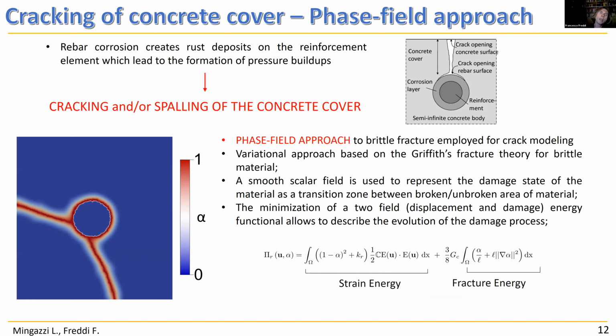So once the expansion and the swelling is determined, the fracture process has been studied with a smeared approach. I don't know if you are familiar, just a few words. The sharp approach to fracture is extremely complex because the most difficult thing is the position of fracture that is unknown. So it's much more easy to study, especially from the computational point of view, this problem with the phase field approach or the damage approach.